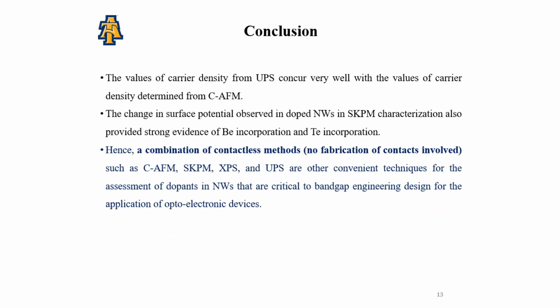Conclusion. The values of carrier density from UPS concur very well with the values of carrier density determined from C-AFM. The change in surface potential observed in doped nanowires in SKPM characterization also provided strong evidence of beryllium incorporation and tellurium incorporation. Hence, a combination of contactless methods where no fabrication of contacts is involved, such as C-AFM, SKPM, XPS, and UPS, are convenient techniques for the assessment of dopants in nanowires that are critical to band gap engineering design for the application of optoelectronic devices.